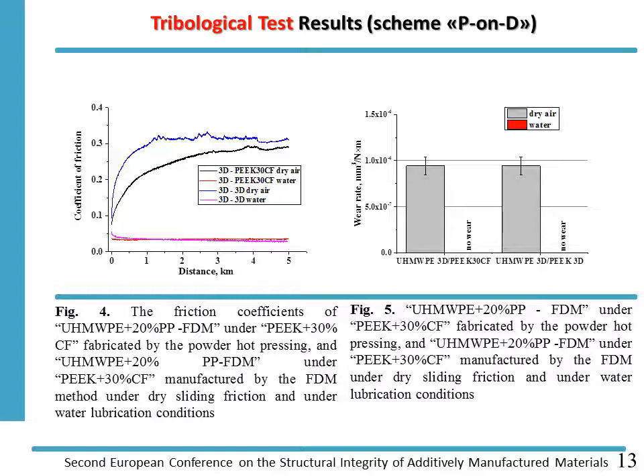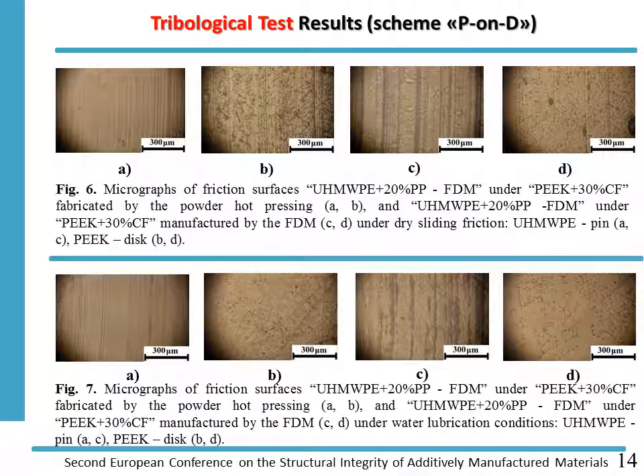And on the right you see the data for the wear rate for both specimens. For dry sliding, it is nearly the same level of wear intensity or wear factor, and practically no wear is registered for water lubrication. It just explains that the parts produced by fused deposition modeling might be efficiently used for such an application.